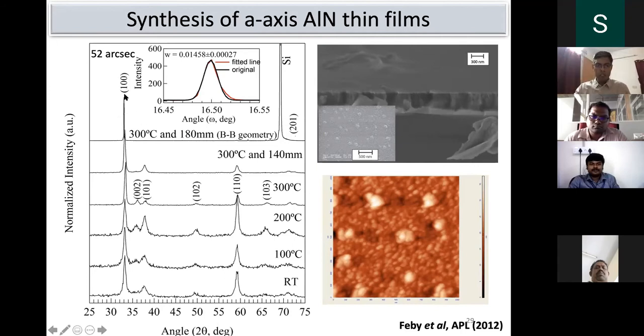The intensity is very small. That's why you see the silicon peak is very high, which is missing here. You can completely isolate the silicon substrate peak when you keep the incident angle at 0.5 or less. But in the case of powder XRD, you cannot miss it. The X-ray will penetrate into the film and go to the substrate.